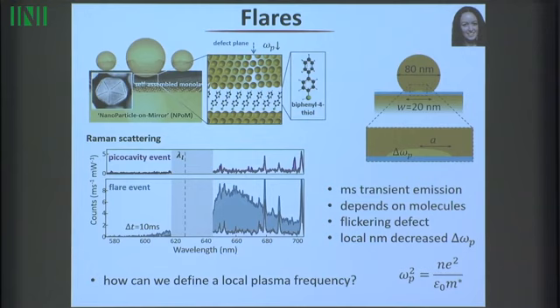So for instance, in recent work, I'm showing the same sort of Raman spectrum here. This is the sort of event I showed you before where a new line appears, which is coming about because one of the gold atoms has moved and it's changing one of the bonds here. We can measure it. But sometimes we see something completely different. We see something sort of glow very briefly. And it's only because we're looking at very small volumes of space we're able to see these things going on. This is a sort of looking at materials on the nanoscale, and it beats any electron microscopy that we can do because it's so fast.